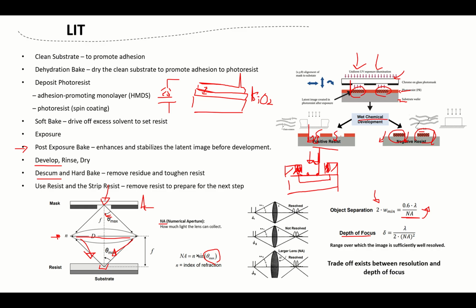And here's another concept, which is the depth of focus, defined as the range over the wafer in which the image can be sufficiently well resolved. If this is really small, it means that the process will be really hard, since there's not much range for the image to be resolved. As we can see, if NA increases, the depth of focus will decrease. But we also want the resolution to be as small as possible so we can separate the objects. However, if we increase NA, the depth of focus decreases, meaning the acceptable range for the image to be resolved becomes smaller. So there will be a trade-off between resolution and depth of focus.